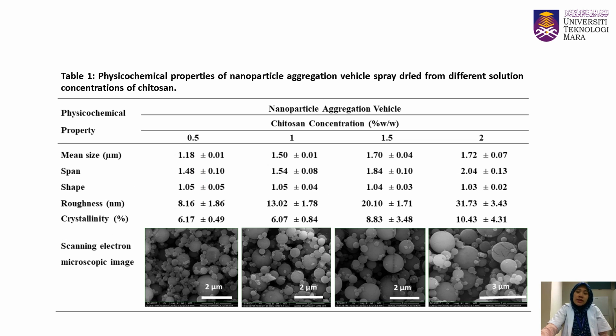What about nanoparticle aggregation vehicles? This slide shows aggregation vehicles prepared via nanospray drying of chitosan at different solution concentrations. Here you can see that the size span is generally larger when a more concentrated chitosan solution was used to prepare the aggregation vehicle. The surface texture of particles gets rougher when a higher chitosan solution concentration is used, and likewise for the crystallinity.